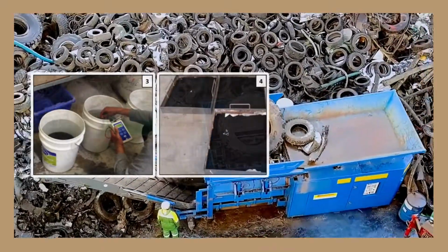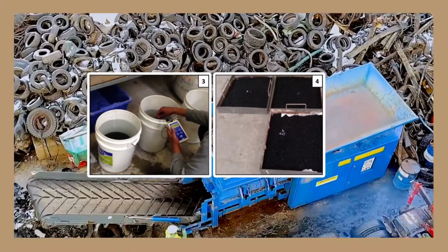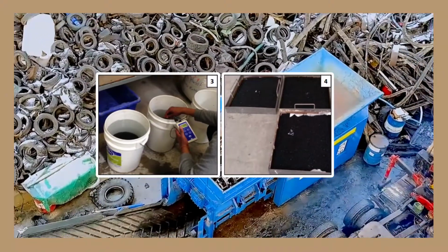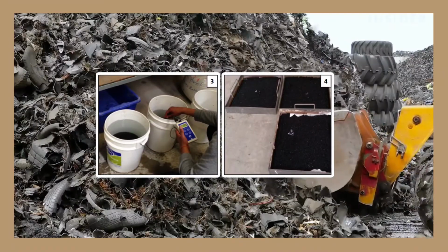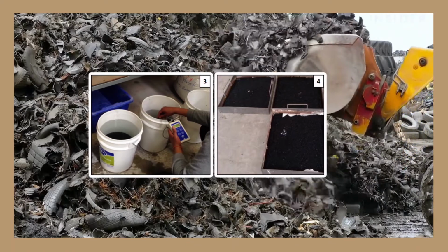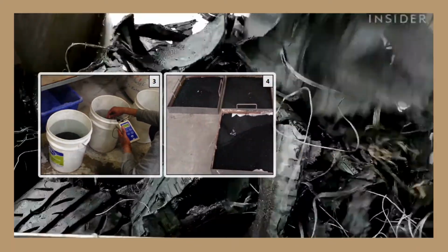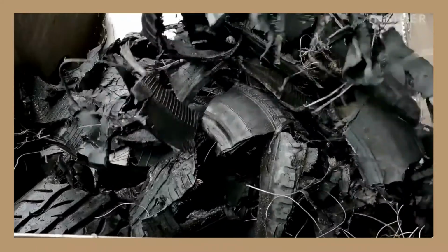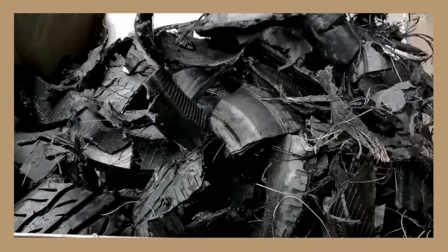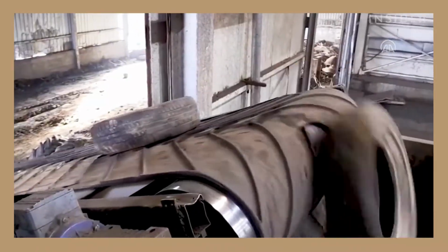The crumb rubber is prepared by washing it in tap water to remove all particulates before submerging it in a concentration of NaOH. After submerging, the crumb rubber particles are washed again by constant agitation of tap water through stirring until the pH level reaches 7, which takes at least 30 to 45 minutes, and then they are left to be air dried.